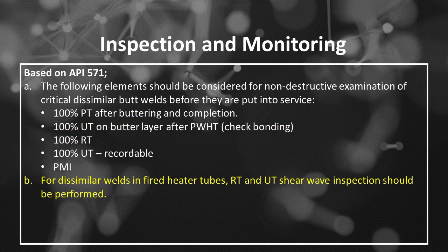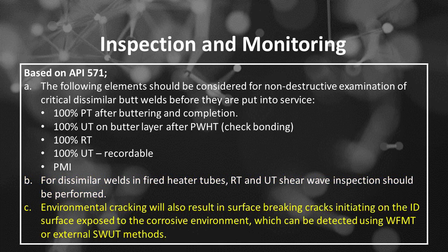The second is for dissimilar welds in fired heater tubes. RT and UT shear wave inspection should be performed. The third is environmental cracking will also result in surface breaking cracks initiating on the ID surface exposed to the corrosive environment, which can be detected using WFMT or external SWUT methods.